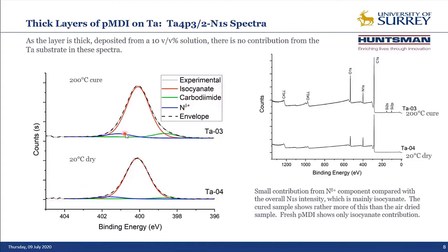But actually, this is just donor-acceptor or acid-base interactions, and it's the self-association of the isocyanate molecules themselves. And what we've got to bear in mind here is the relative intensity of the isocyanate peak with this peak. And this is really a very minor component. It might be of the order of 10% in intensity.